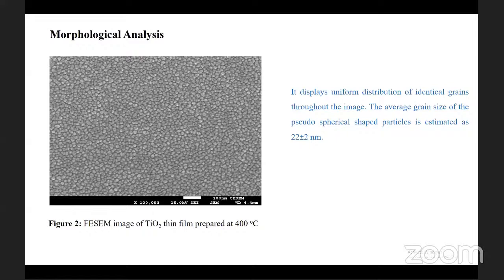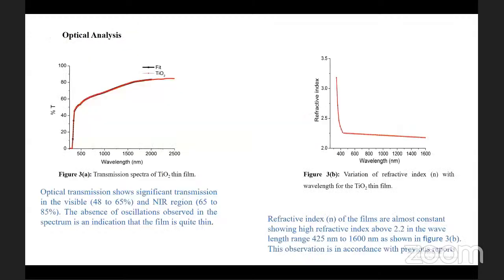Morphological analysis. The FESEM image of TiO2 thin film prepared at 400 degrees centigrade is demonstrated here. It displays uniform distribution of identical grains throughout the image. The average grain size of the pseudo-spherical shaped particles is estimated as 22 plus or minus 2 nanometers.